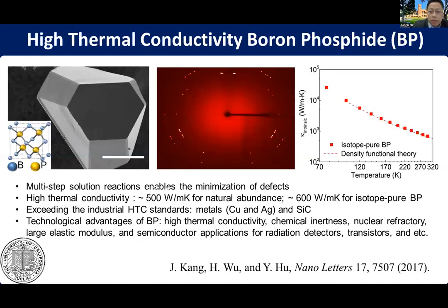So the first candidate is cubic boron phosphide. My group was able to develop multi-step solution reactions to achieve high quality crystals. And we did thermal transport measurement. The thermal conductivity for boron phosphide is around 500 watt per meter Kelvin for natural abundance and 600 watt per meter Kelvin for isotope pure, exceeding the industrial standard and most metals and silicon carbide.